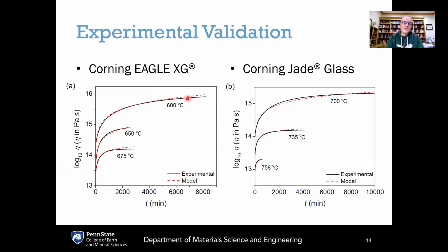For example, in this case, for an isothermal hold at 600 degrees C, the viscosity is starting out at 10 to the 13.5 or so, and then it is increasing all the way up to close to 10 to the 16 Pascal seconds over this time period of 8,000 minutes. If the isothermal holds are at higher temperatures, that increase of the viscosity happens more rapidly.